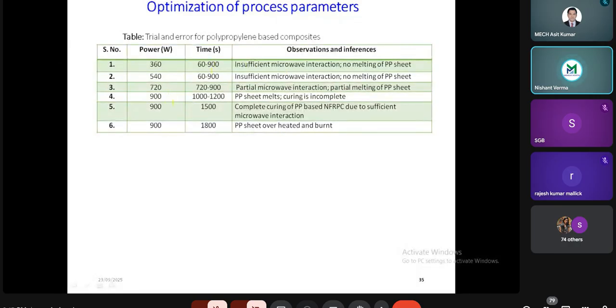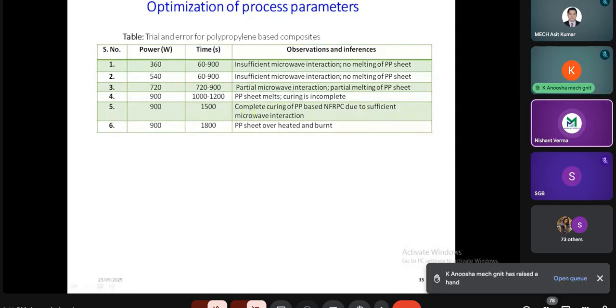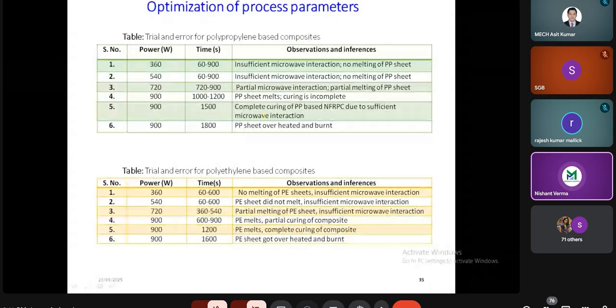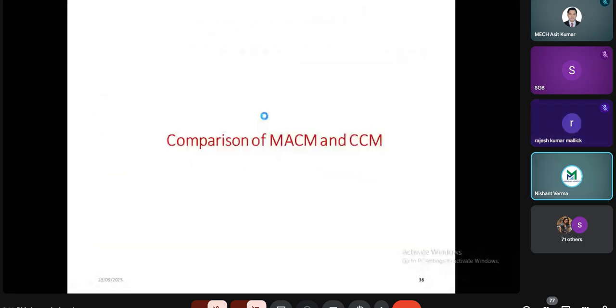In the case of 900, the PP sheet melts and curing is incomplete. When we increased the time to 1500, complete curing of the matrix takes place. And in the case of 1800, the PP sheets overheated and burned in the microwave. So in this way we have optimized it. So this is very important.